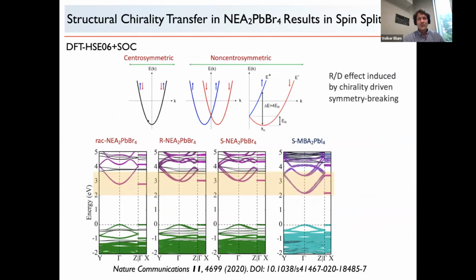What you see is that if the material was centrosymmetric, you would get 1 band. If you break the symmetry, you actually get 2 bands where the color indicates the spin character. So these energy bands suddenly have defined spin character. This is called Rashba or Dresselhaus splitting. And we see this kind of splitting here in the band structure that we calculate for the symmetry broken materials, and we can quantify this and do more analysis. And so this has been ongoing work in our group for many years.